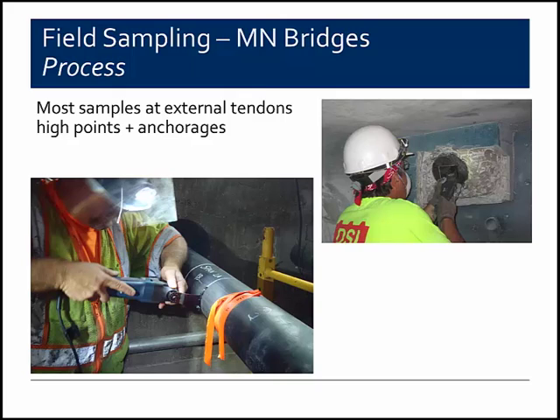So the field work, as mentioned, generally involved opening external tendons and anchorages. External tendons were preferred because it was much quicker to open them up and get a sample out, also much easier to repair. And a sample opening of an external tendon is shown in the photo in the lower left. At certain bridges where external tendons were not present, or for other considerations, occasionally certain grout lots were accessed at the anchorages, which the photo in the upper right reflects, where a certain amount of the pour back was removed to expose the plastic grout cap. The grout cap was cut and grout was removed, and then everything was put back together.